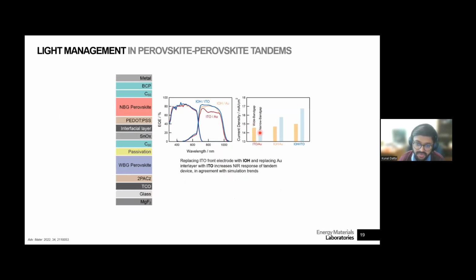between the two cells, so the wide bandgap and the narrow bandgap, you are starting from a mismatch, and then quite soon you actually have a mismatch in the other direction. So now your wide bandgap is a limiting subcell, and then when you go a step further, the mismatch gets even worse. But you can improve it afterwards by working more on the wide bandgap side.